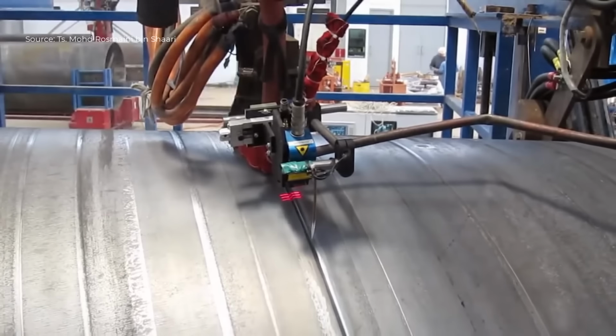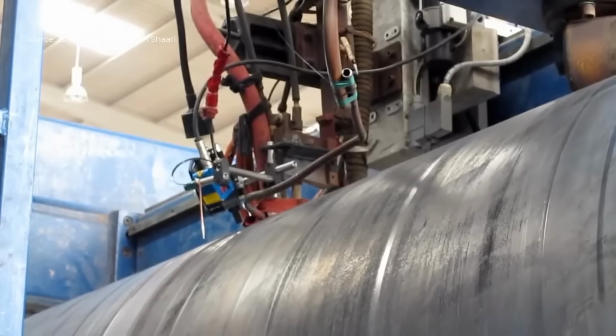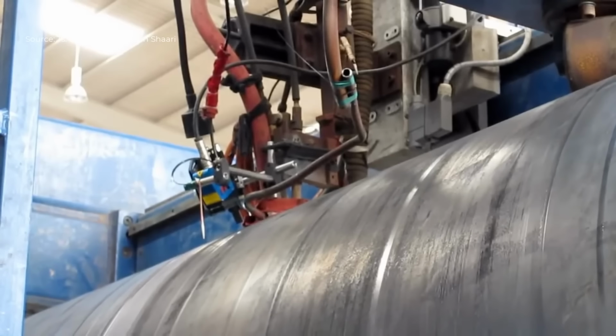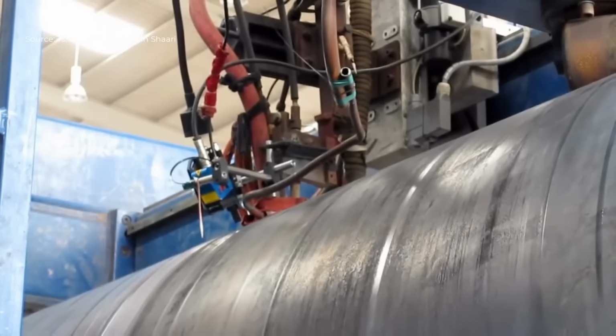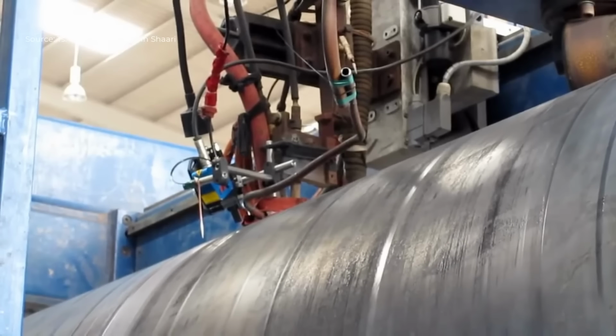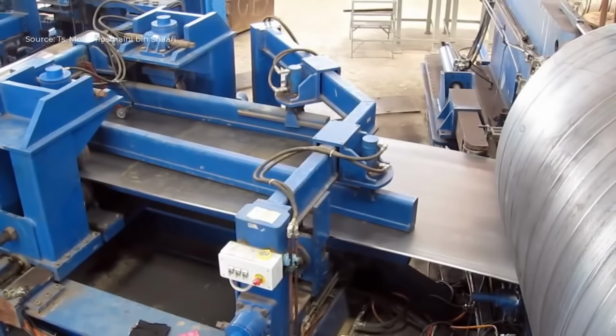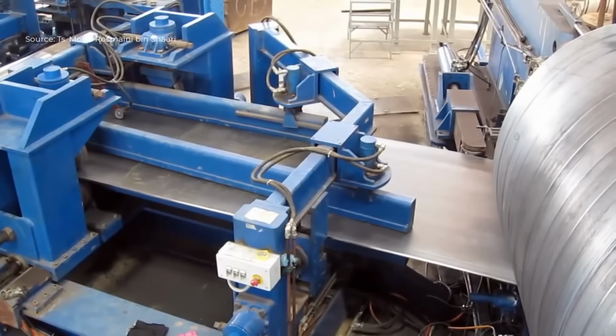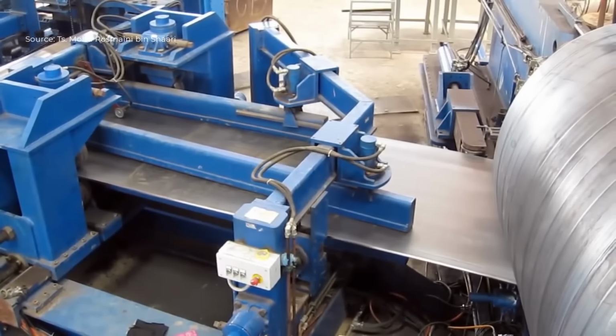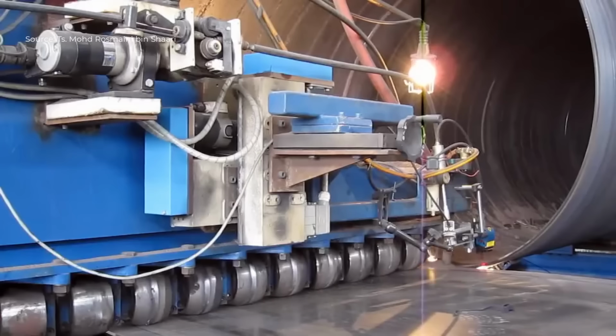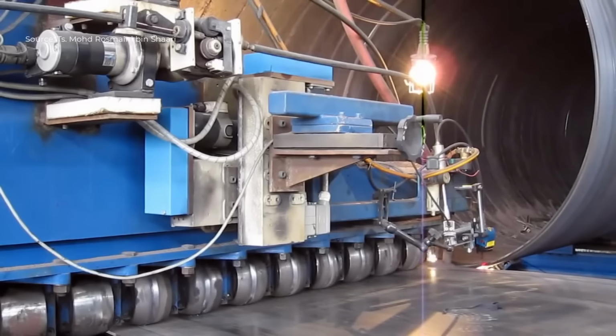First, the outer seam of the spiral pipe is welded using automatic submerged arc welding technology. A continuous welding wire is fed automatically into the welding head, while granular flux is deposited over the weld zone. When the electric arc is generated beneath the flux layer, the arc melts both the wire and the base metal edges, forming a strong and uniform weld bead.